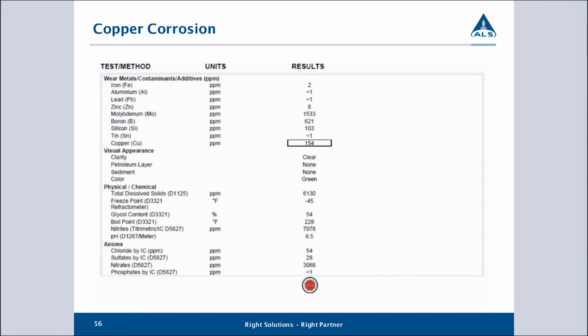All right, here we have a coolant that is driving a lot of copper corrosion. So iron isn't corroding, but copper is. Now, I can also see that our additive levels suggest that this is a conventional coolant, and it is extremely heavily dosed with sodium nitrite. And a lot of this is converted. So it suggests this coolant has been in use for a long time.